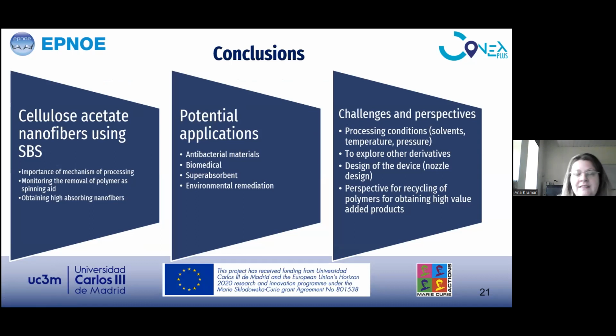today I showed you that it is possible to process cellulose acetate nanofibers using solution blow spinning, but also that the mechanism of processing is very important, and it's important to monitor the removal of the polymer which we are using as a spinning aid. I showed you that it is possible to obtain highly absorbing nanofibers, and these nanofibers can have potential application as antibacterial materials in biomedical applications. They can have application, for example, in hygiene products because they are super absorbent, and also because of their high absorbing capacity, they can possibly have potential application as environmental remediation material, and this will be, of course,